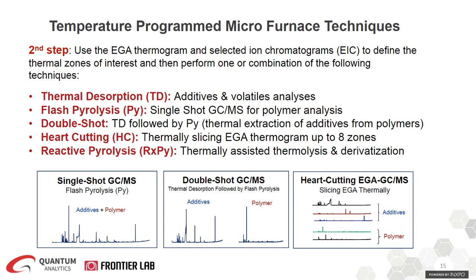So now to further analyze your sample, the second step is to perform any of these methods here or a combination of them. So you could perform thermal desorption. This technique mostly is for analyzing additives and volatiles, but the key point here is that the additives and volatiles are thermally extracted from the mixture. So instead of performing any solvent extraction or sample preparation, you actually thermally extract the additives from the mixture or the polymers. Or you could also perform flash pyrolysis.